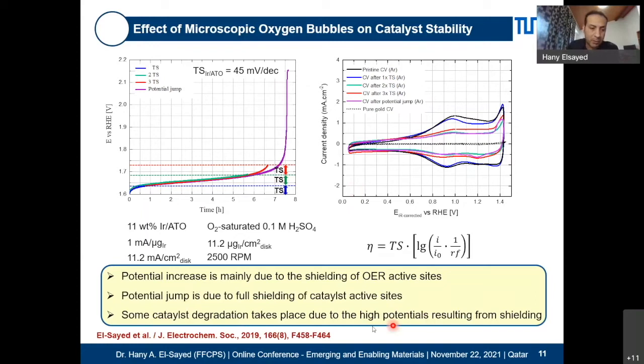So let me just read this out loud: the potential increase that we see here is mainly due to the shielding of oxygen evolution, the OER active sites being blocked. And this potential jump is most likely due to the complete shielding of the catalyst layer. So some catalyst degradation, of course, happens in this case, but this is basically induced because of the shielding. The shielding is making the potential go to higher potential, and it's inducing degradation. If the shielding is not happening, the higher potential will not be reached, and the degradation will not even happen. So this is what we call artifact-induced degradation.